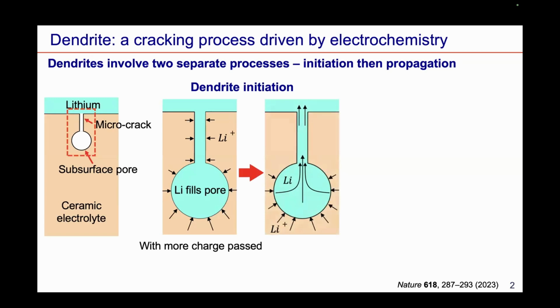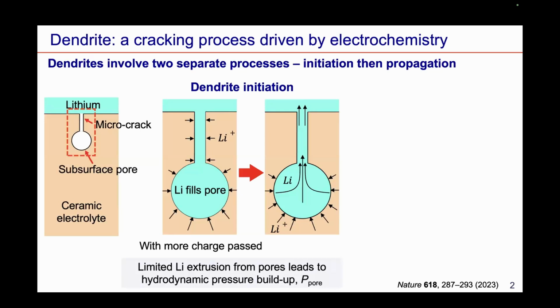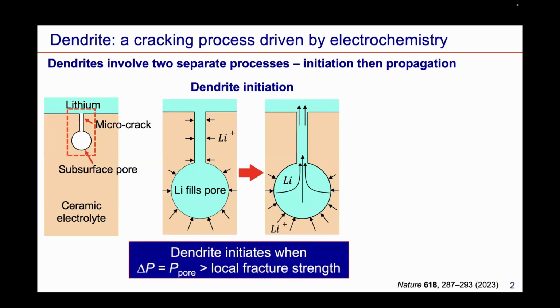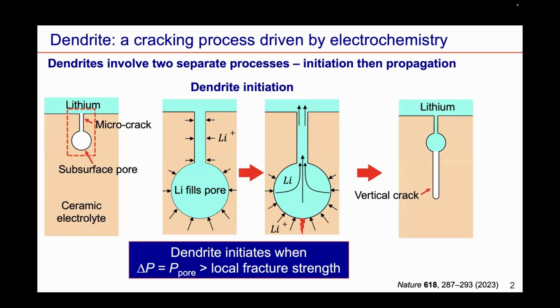Further lithium deposition will induce a stress within this defect structure and also a pressure buildup within this pore. This pressure buildup will lead to lithium extrusion back to the electrolyte surface through these micro cracks. And this viscoplastic flow of lithium will induce a hydrodynamic pressure buildup within this defect. When we charge the battery at a sufficiently high current density, this pressure buildup may exceed the local fracture strength of the ceramic, and this will induce electrolyte crack initiation in the form of a vertical crack below this pore.